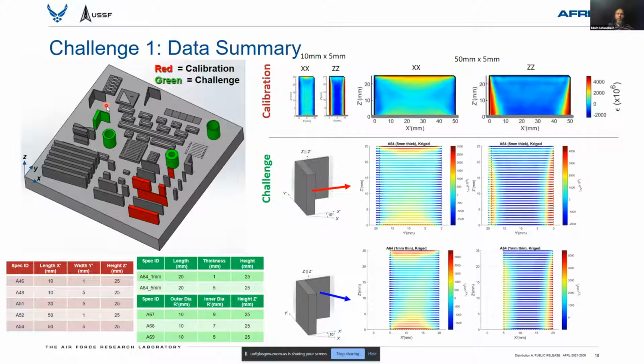So here we provided the calibration data. We've also provided descriptions of the processing parameters, the typical parameters you'd imagine for laser powder bed fusion, and a relatively basic description of the scan strategy. And then we asked folks to make predictions for these green parts. So I'm showing on the bottom half of this screen some of the validation data now, the measured residual strains in these components.